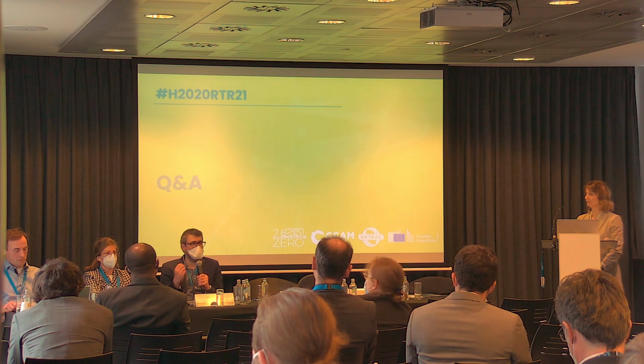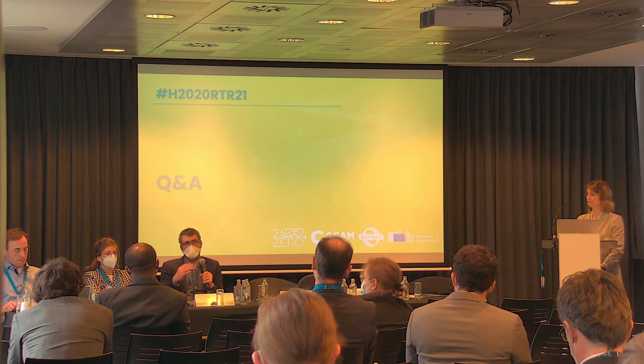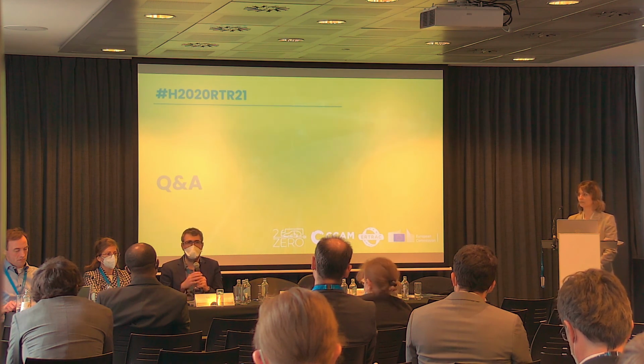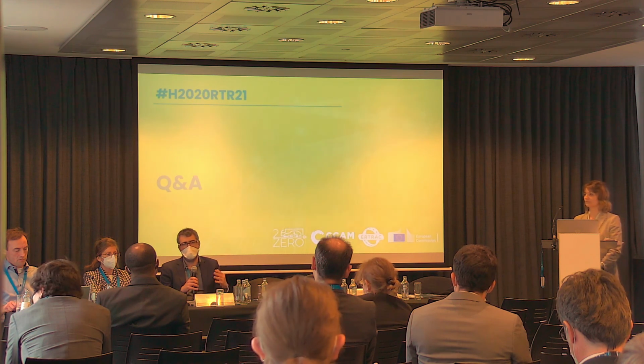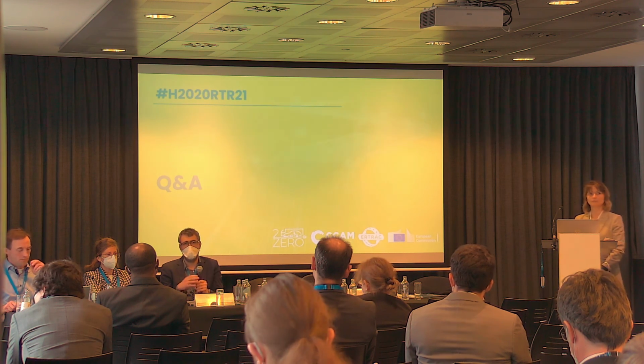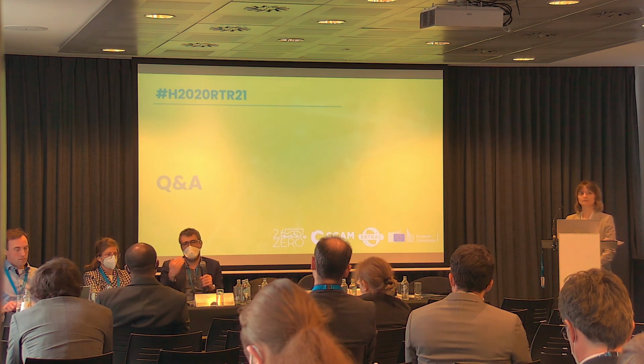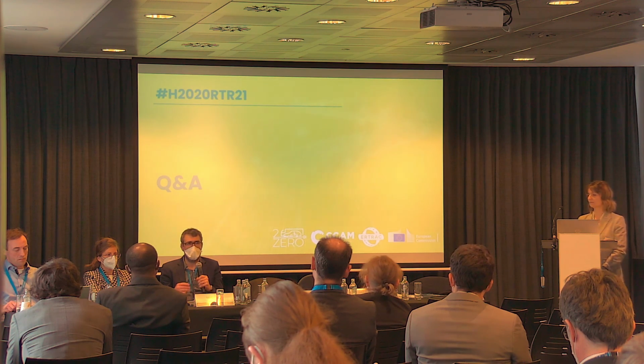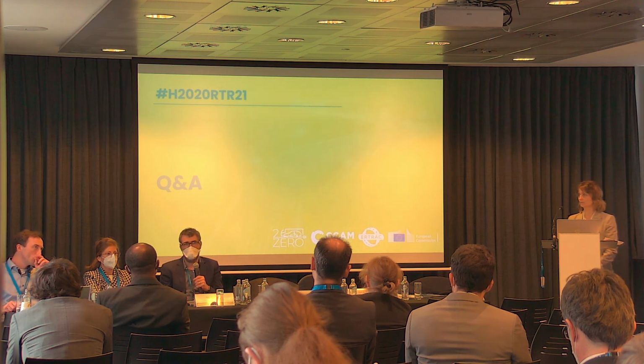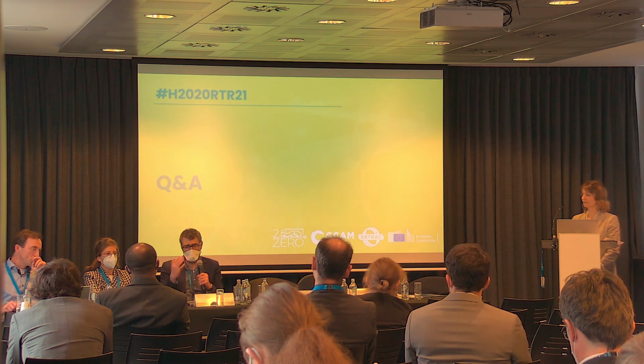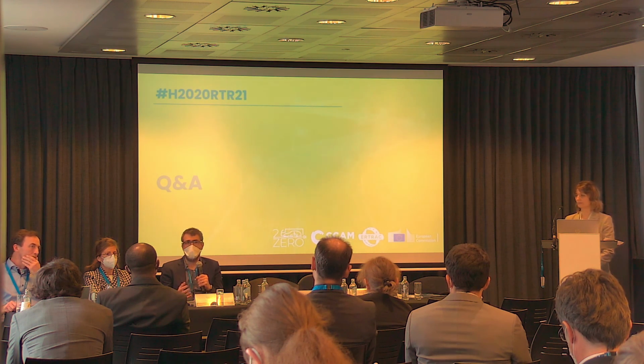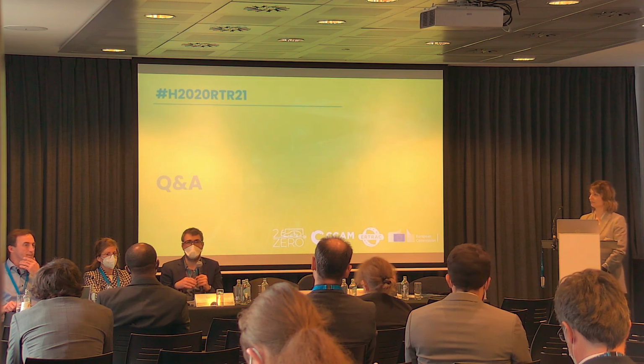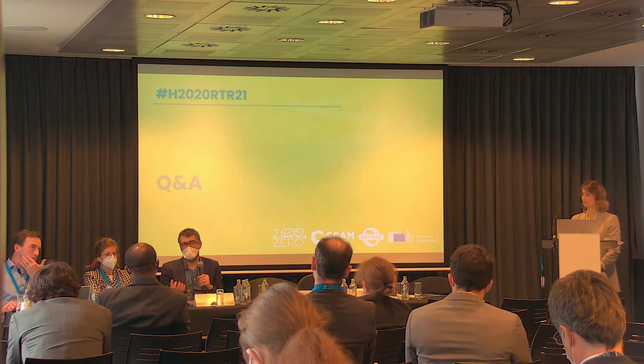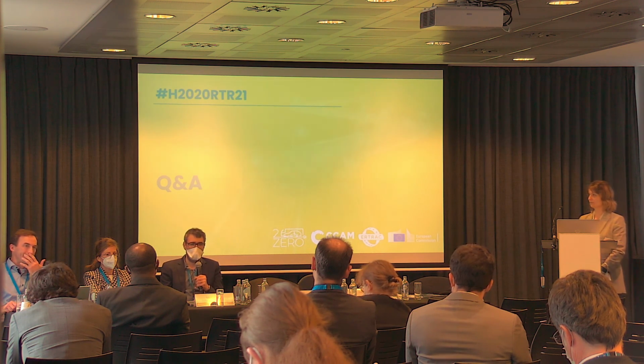So for instance, what we can see for the moment is that we have two phases in the charging of the battery. The first phase where the silicon is charging, and the second phase where the graphite is loading. And we can see a change in the swelling rate of the battery due to this repartition. And if we change the charging rate, this swelling will change also. And if we change the amount of silicon, there will be a change in this kind of behavior.